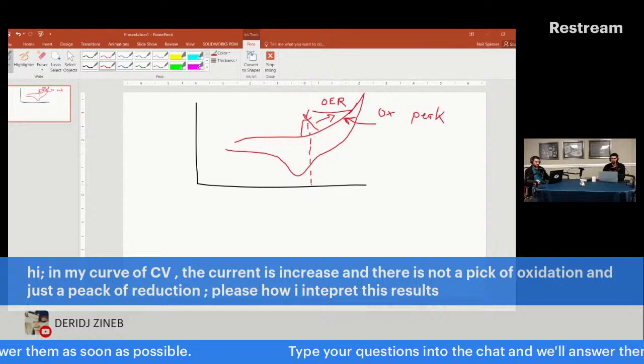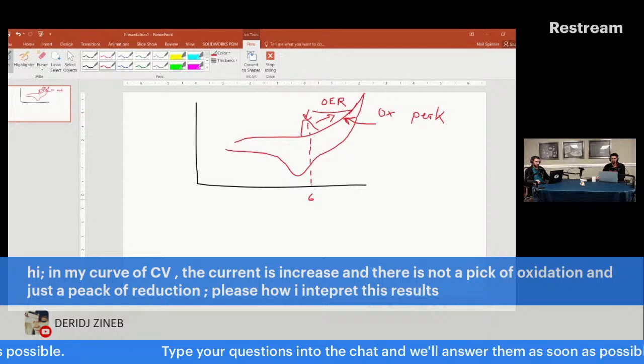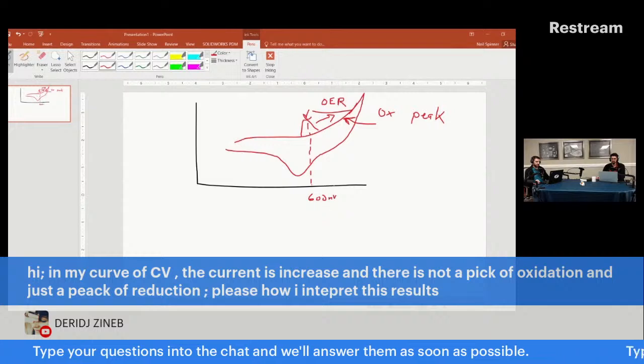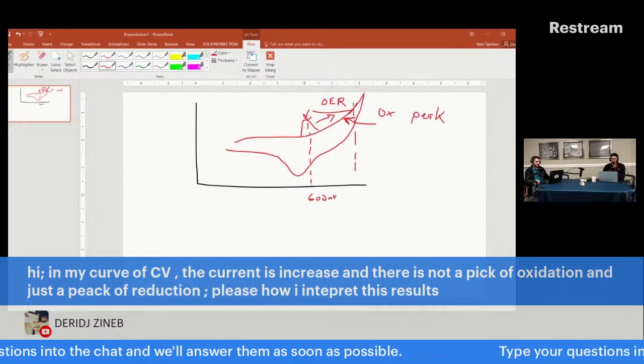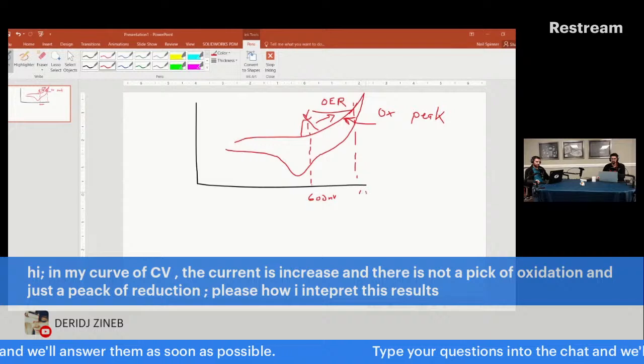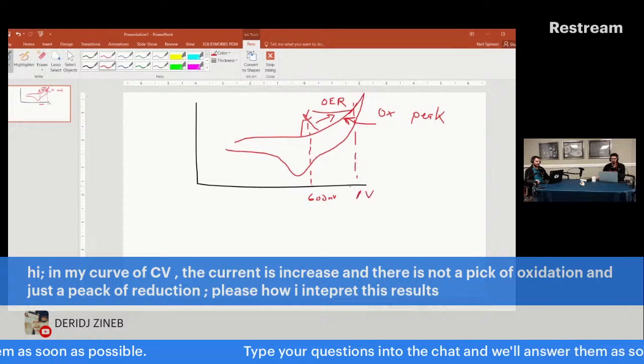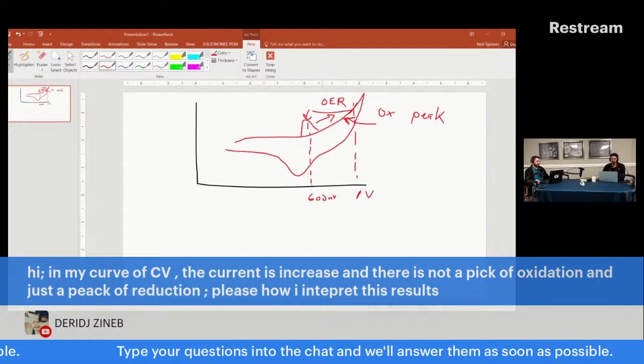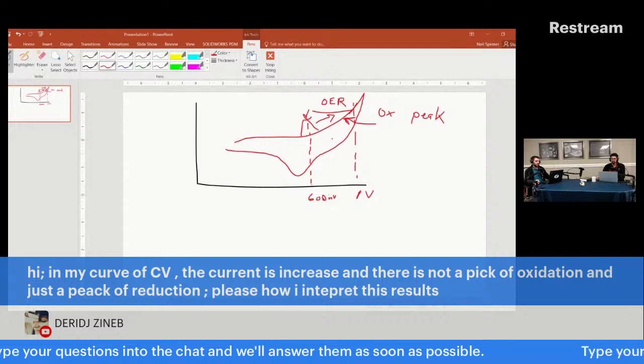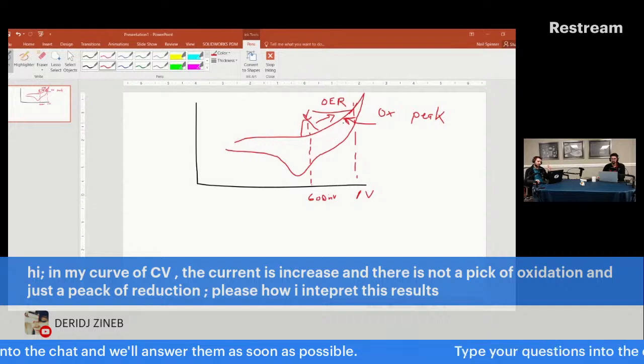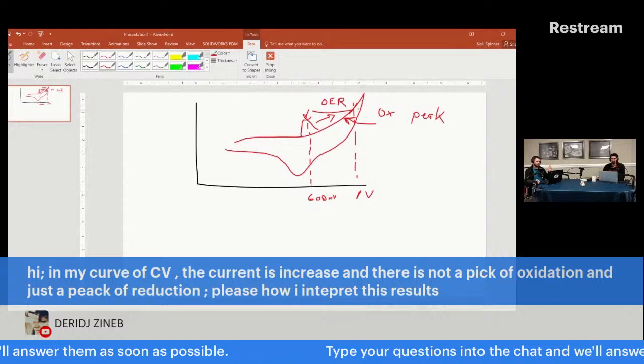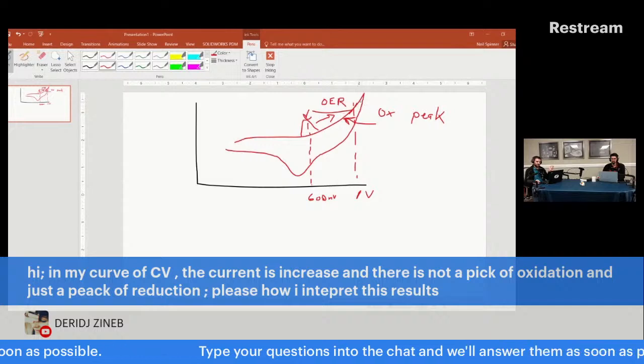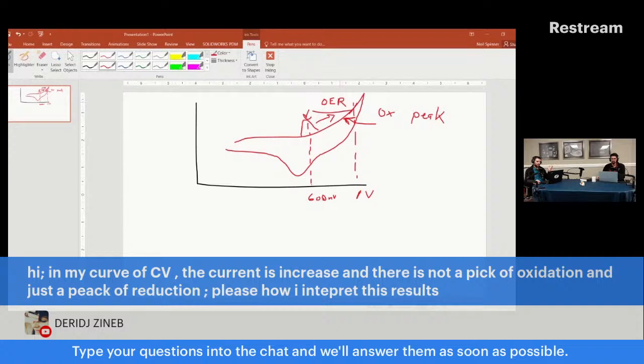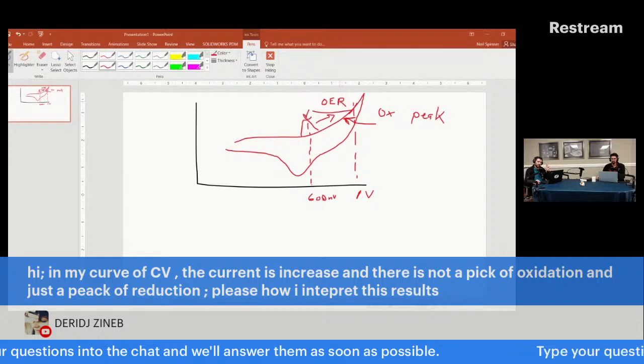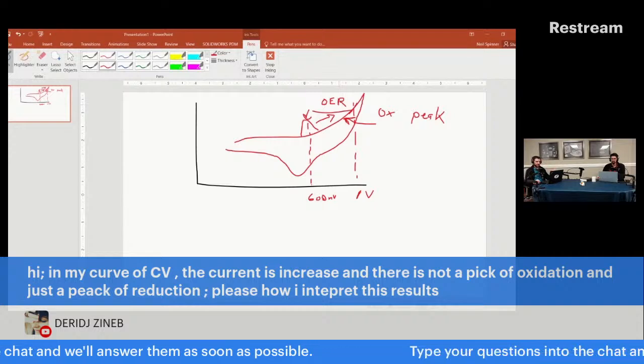This right here might be, whatever, 600 millivolts, right? And then instead it takes until 1 volt to oxidize. So it's like I have a high overpotential. My catalyst isn't doing a very good job. So the reality is that the oxidation peak won't resolve because I have to go much more positive, and by that point I'm already at the limit of my electrolyte, which is in this case aqueous.